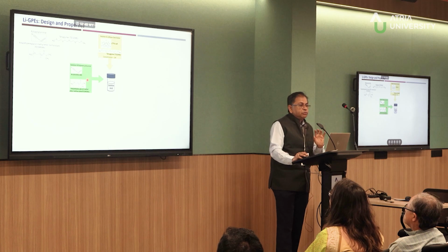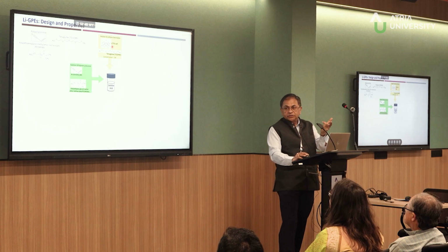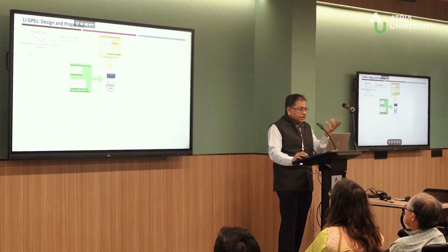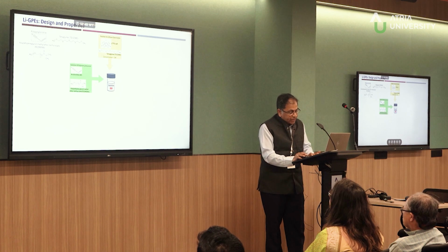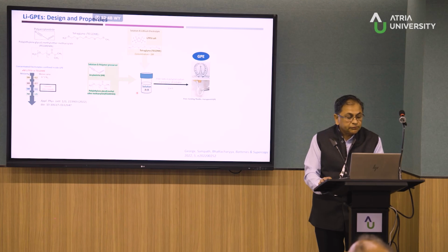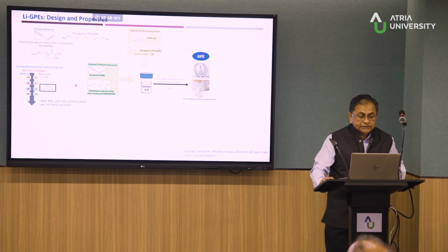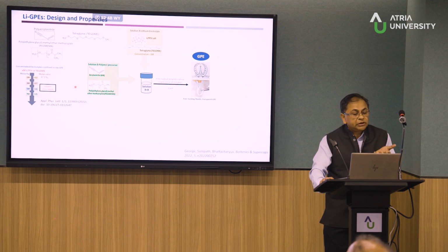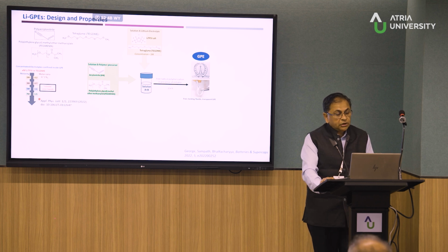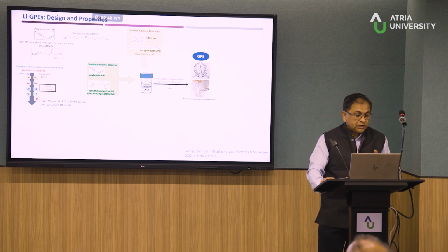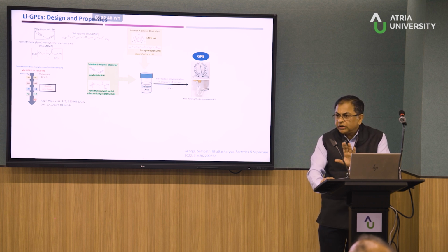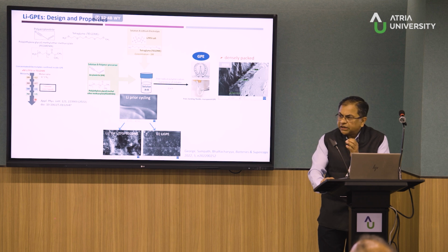this is the polymer component which will give you the scaffold, but you also need the liquid electrolyte where you need the conductivity. So when you put this in a bottle like this, you do the polymerization reaction, you get very nice films, and of course we have done this over the last decade or so. We're getting all these papers on very high concentrated liquid electrolytes. So you can actually also make these polymers with very high concentrations of the salts. Okay, so what we are trying to solve here is, these are really compact structures.